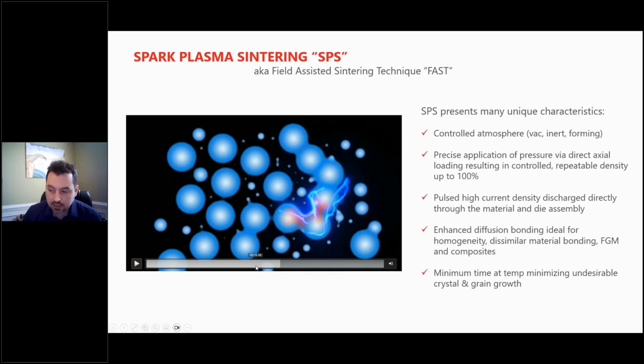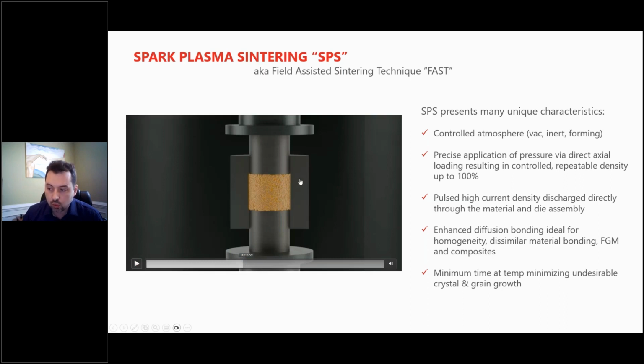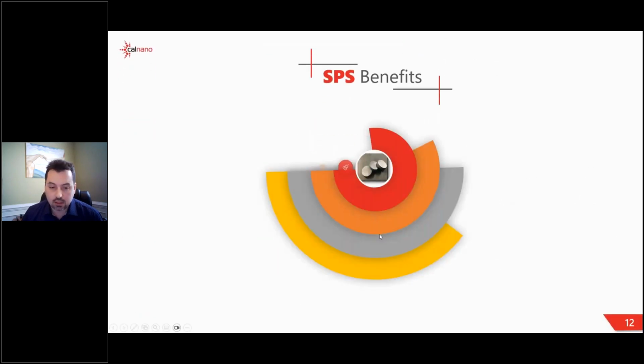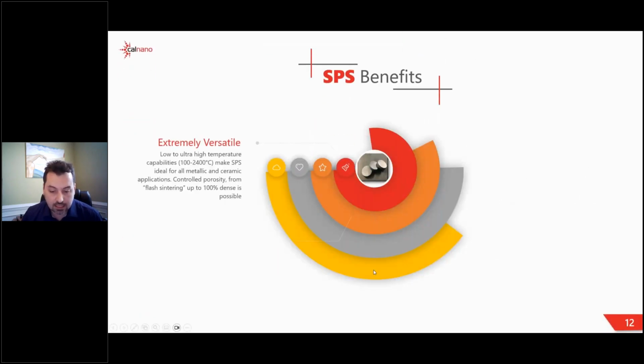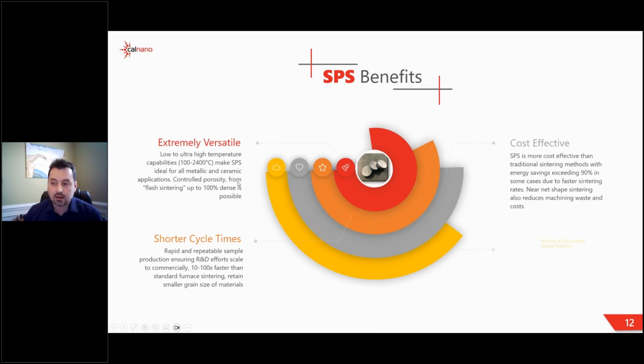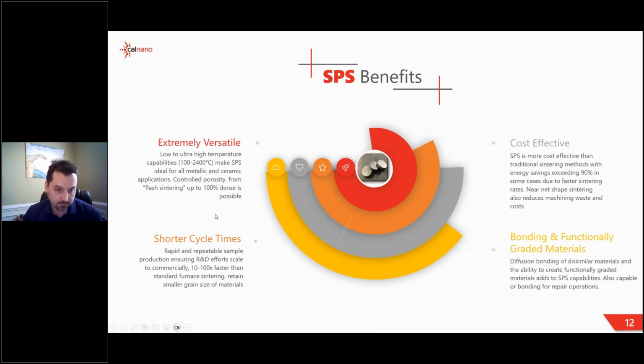We are actually using the material itself or the tooling, in the case of a non-conductive powder, as the heating element. So given there is no heating elements in the furnace, that gives us an extreme versatility. And that allows us to have no theoretical maximum temperature. The highest temperature is really just the graphite itself or the material. We often run north of 2000 degrees Celsius. There's just not too many applications needing higher than that. But we also don't have a minimum.